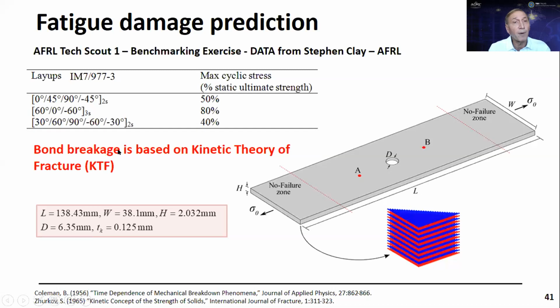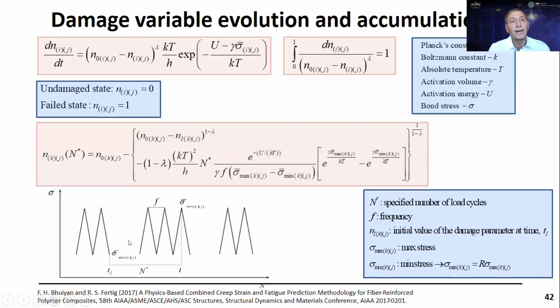And we applied bond breakage based on the kinetic theory of fracture here. So in the composite peridynamic model, we modeled each ply through the bonds, as I mentioned before. Also, we have bonds in between the layers. The kinetic theory of fracture was introduced by Coleman and Zhurkov in the 60s. And then later on, Fertig applied it to composites. So just one slide on the damage variable and accumulation of basically the state variable that I have, N.